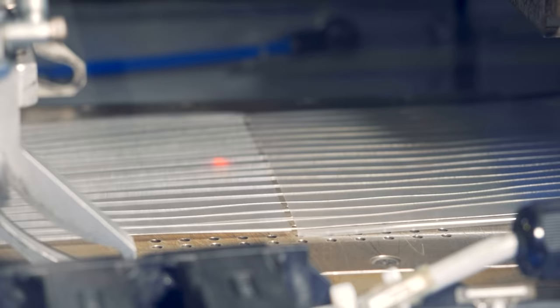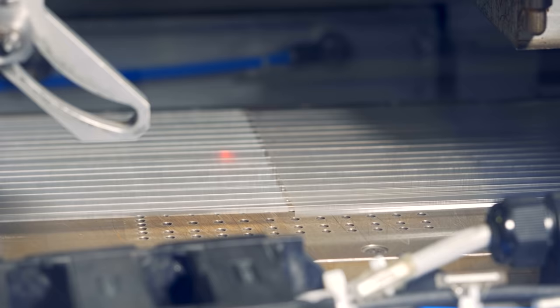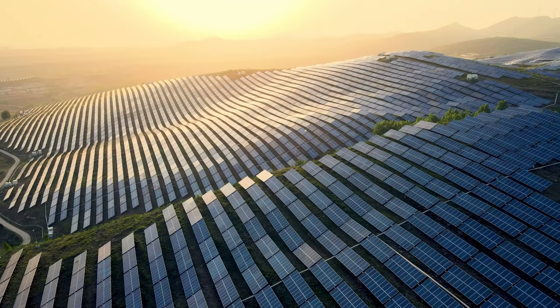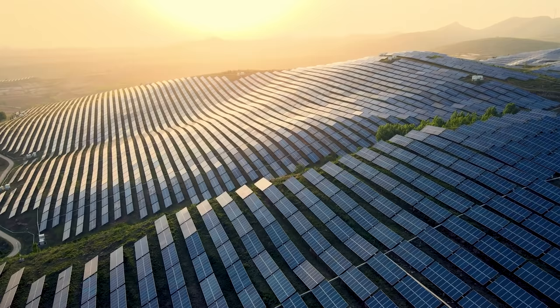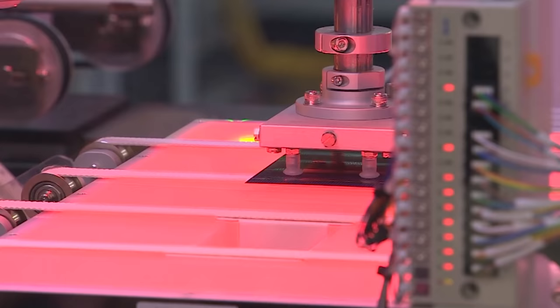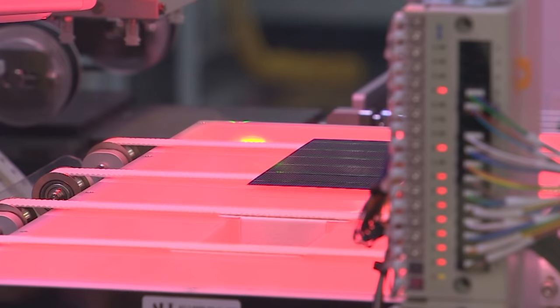Once all the cells are in place, another layer of EVA is added over the panel, and an additional backsheet is added to encapsulate the cells and internal wiring. The next stage is called pre-lamination electroluminescence. Exploiting one curious property of photovoltaic cells, that they light up whenever a current is passed through them, inspectors can look even closer for micro-cracks that might render the final panel inefficient or, at worst, useless.